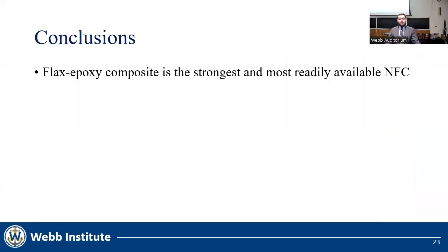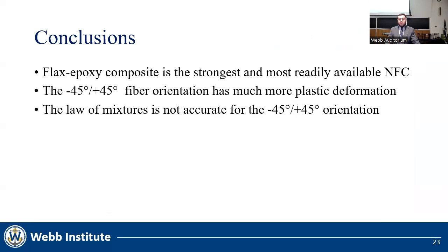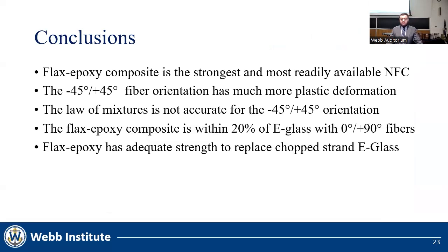Some conclusions of my research are that the 45-degree fiber orientation has much more plastic deformation due to the stress being placed more on the matrix. This results in large inaccuracies when utilizing the law of mixtures. The strength of the composite is within 20% of the chopped strand E-glass composite, which means it has adequate strength to replace chopped strand E-glass when utilizing stronger fiber orientations, as long as the yacht builder is willing to sacrifice ease of construction for a more sustainable composite.